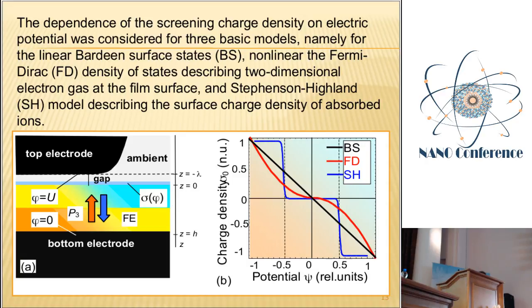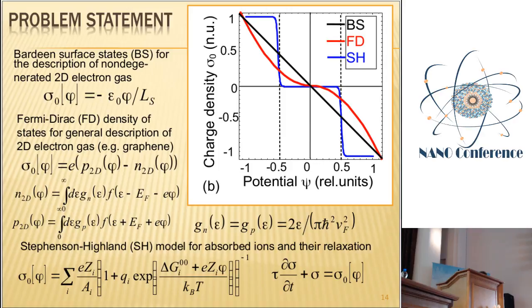Well, very briefly, the first case is linear charge density, the second and third models are nonlinear charge density, but in the case of the Stephenson-Highland model, we have exponential nonlinearity, and what will be important for understanding the obtained results is that the ion formation energy can be different for positive and negative charge species. It can be equal, but it can be different. All depends on the types of ions which are located at the surface. And a simple relaxation equation for the surface charge. It's a phenomenological equation, of course, we did not derive it, we postulate it.